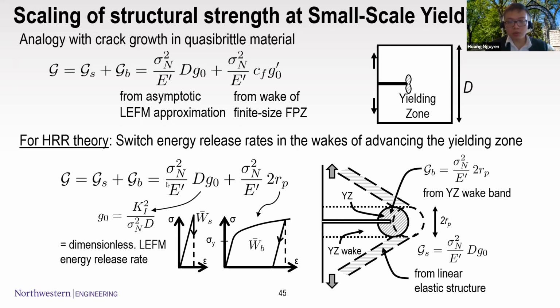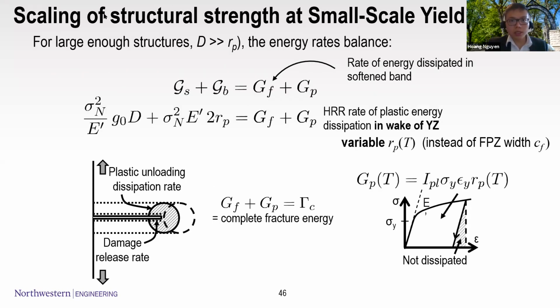And so the energy will come from the part here when you have the release of the elastic energy of the materials, and the release when you have the moving up of the wake of the plastic zone. And also from the material point of view, the energy will be broken up into two parts, the plastic part and also the part from the fracture process zone, which is a micron in scale here.